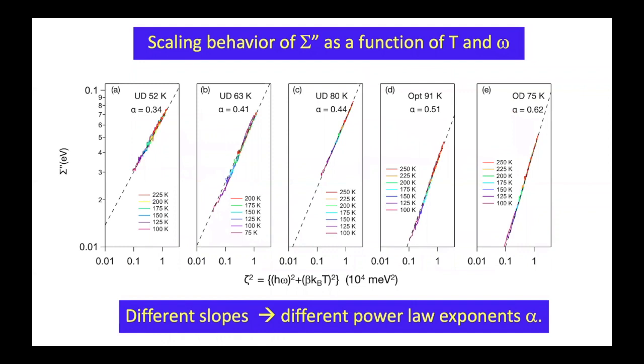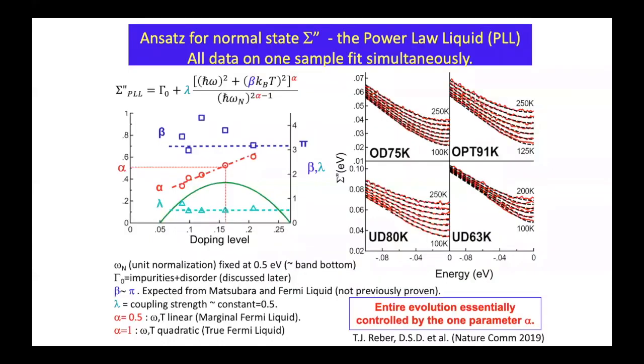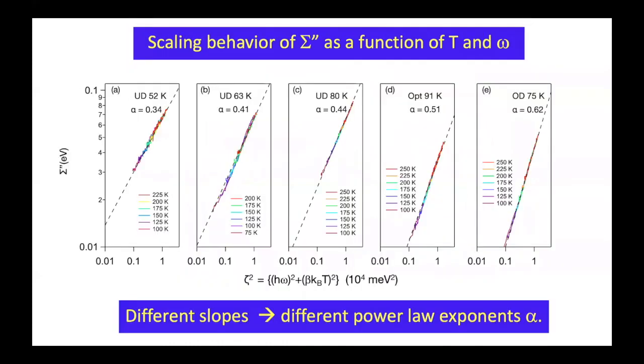Okay, so we have all this data from many temperatures, many frequencies, etc. We scale them according to this thing inside here. And I call that thing inside C squared. There's a thing inside for the different dopings. And all the different temperature curves here now fold onto one set of lines if I do a log plot. And on the log plot, we know the slope is the power law exponent. So the many different cuts, you see they're overlapping here, but they all fall on the same line. And you see the slopes, my alpha, vary smoothly from overdoped to optimal doped to underdoped. So it's about 0.5.